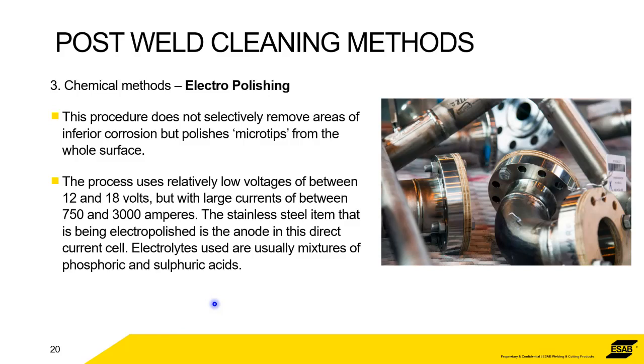You're setting up a potential difference across there within a media, an electrolyte, I should say, and that removes the microtips, as we call it, from the whole surface of the part that's being treated. So it's an electropolishing of everything. So it'll polish the unwelded areas just as much as it will polish the welded areas, the weld beads, the heat affected zones. It treats everything the same.